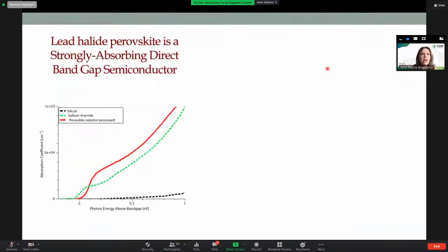In terms of absorption, if you compare with, for instance, silicon, which is the black curve here, the perovskite is the red one. You can see that because the perovskite is a direct band gap, it has much higher absorption, even compared to gallium arsenide, which is part of the first generation.